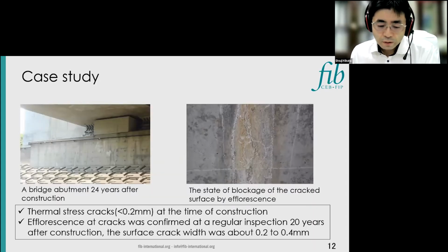So here goes into the case study description. The target structure was a bridge abutment on a national highway that had been built on the plains in the cold, snowy region 24 years ago. At the time of construction, cracks had occurred due to temperature stress, but the surface crack width was less than 0.2 millimeters, so this structure was not repaired immediately and it was kept under observation.